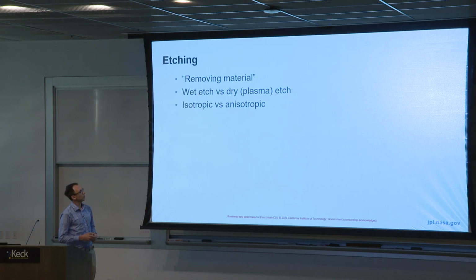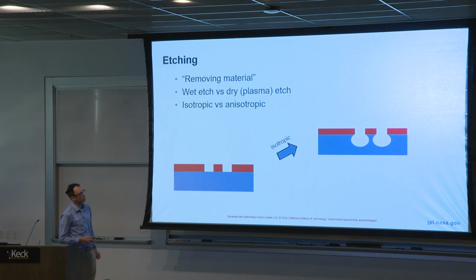Another thing that's going to be important when we talk about metasurface fabrication is isotropic versus anisotropic etching. So if you have a blue material that's patterned and you have a photoresist pattern on top, if you do an isotropic etching, typically you end up with something looking like that. That's often, at least for metasurfaces, not what you want. Typically, you would want to have very nice and vertical sidewalls, but the isotropic wet etch, while etching vertically, will also etch laterally and start undercutting your mask. And you can imagine if I have this in the etchant for too long, this whole feature is just going to disappear.